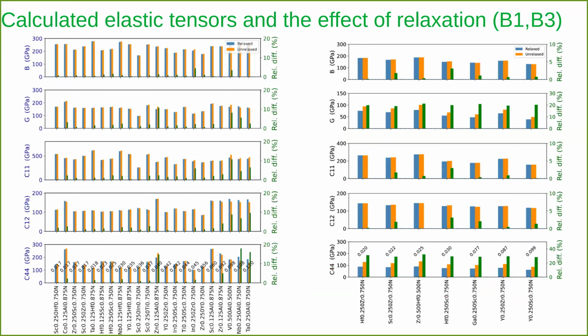And then if you come to the elastic constants, yes, we are happy with those, with what we can actually manage and calculate. Here you can see the calculated values. I just wanted to show the different alloys. If you see any magnetic cases like cobalt, you should note that it's a non-magnetic calculation. So we calculate the elastic constants.